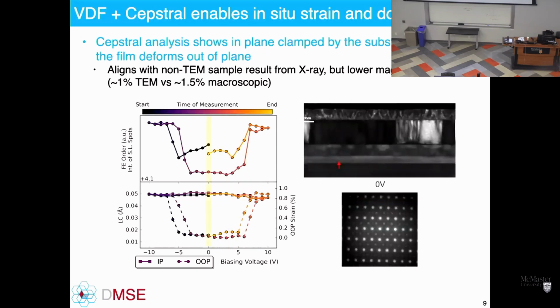And it's through substrate clamping, in this case, that we actually force all of the strain to go out of plane from growing along this direction. And so this is basically a percent of strain that is in roughly the same comparison to what's measured macroscopically.